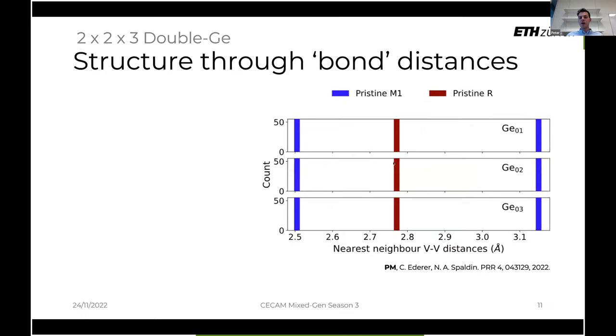And so now I want to look at particular configurations in more detail. As a measure, I would like to use bond distances, or nearest neighbor vanadium-vanadium distances, where I select three specific configurations, GE01, GE02, GE03, which are along the chain. What I'm showing in dark blue and dark red are the pristine crystal phases. You see that the monoclinic phase has a fully dimerized structure where we have short bonds and long bonds, and the rutile phase only has one length of bond because it's an equidistant chain.